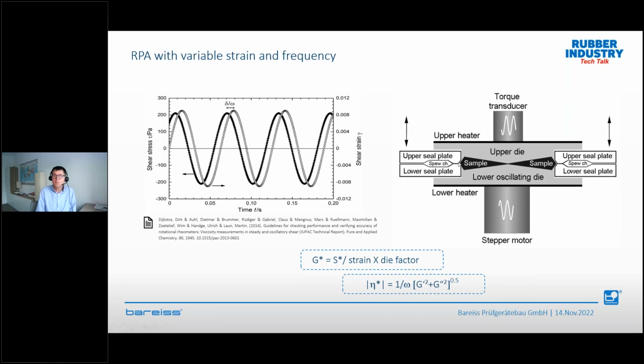This depends on the diameter and the cone angle of our die. The shear modulus is our measured torque value divided by our strain, multiplied by this factor. And when we have this shear modulus, we can calculate our dynamic viscosity from it. That is what you see here. And our omega is 2 pi f, the frequency. And then we have the dynamic viscosity.